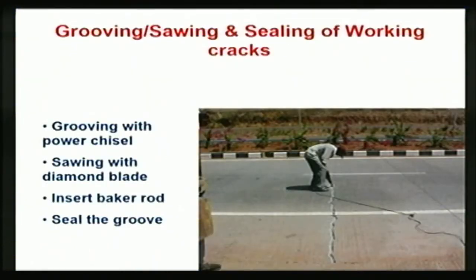But whenever you remove the full depth slab, it is not just the slab, but some extra portion also. Whatever dowel bar assembly is existing on both the sides, that assembly has to be removed also, because during the removal and breaking of the concrete, all the dowel bars may become loose and they will not be effective. So the dowel bars on both the sides of the joint have to be removed, and then the entire patch has to be filled up with fresh concrete, compacted and finished in the same way.